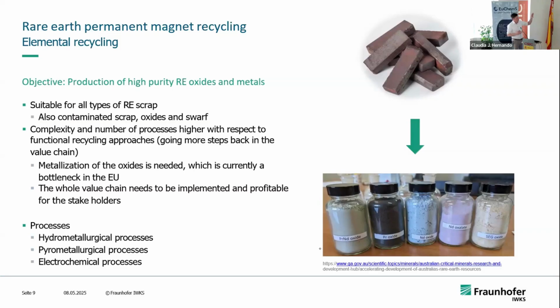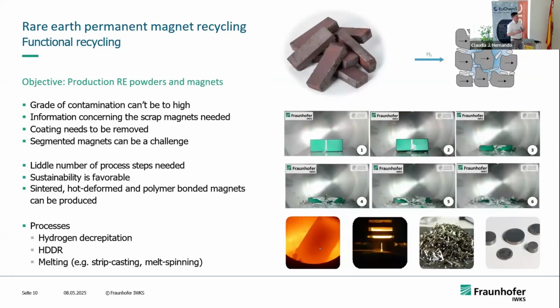Nevertheless, there is a reason to go in this direction, since these oxides, which are produced from scrap magnets, are basically the same as oxides produced from primary mining. So with this, you can produce all types of magnet materials which you need. When you now think about short loop recycling, the difference is that this process depends on the scrap material. So if your scrap is oxidized, it's a problem for the process. The magnetic properties of your recycled product will most likely depend on the magnetic properties of your scrap material. If you have a mixed scrap, it might be harder to implement.